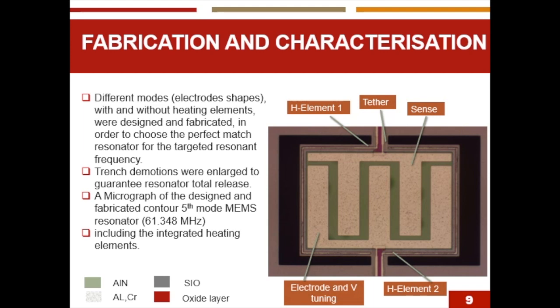Fabrication and characterization. First of all, I have to say different modes, so electrode shapes with and without heating elements were designed and fabricated in order to choose the perfect match resonator for the target resonant frequency. And this micrograph here shows the fabricated resonator which works in the fifth contour mode and gives us a resonant frequency of 61.348 megahertz.